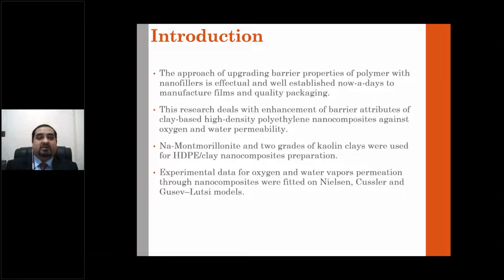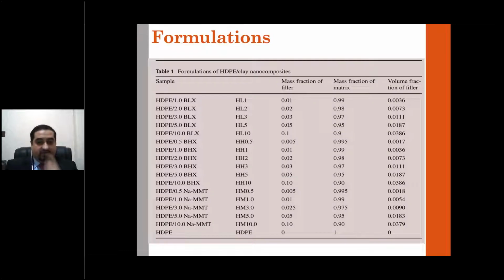Once again, a specialized technique was utilized for pre-blending the nanofillers with polymers without using any compatibilizer. No compatibilizer has been used in any of the case studies that I have discussed. We try to enhance the properties by using specialized pre-blending techniques, and then we utilize the extrusion technique to make sure we get materials with good dispersion and distribution of nanofillers and try to remove as many agglomerates as possible. These were the formulations that we utilized, and we varied the presence of clay from 1 to 10% for the materials under consideration.